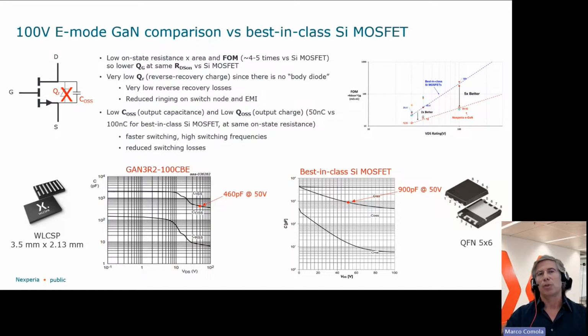And also, I just want to compare our device, that is a GaN FET 100 volt in chip scale package, and you can see the size of the package, 3.5 millimeter by 2 millimeter, close to 2 millimeters, and the output capacitance is 460 picofarad. And instead, you can see the best-in-class silicon MOSFET that is in a package bigger than a chip scale package, 5 by 6 millimeters. It is 900 picofarad at 50 volt. So again, this translates into faster switching and high switching frequency for the gallium nitride product, and reduced switching losses. So again, you increase the efficiency using the gallium nitride.